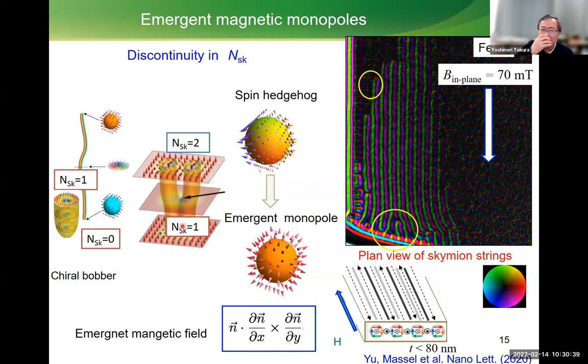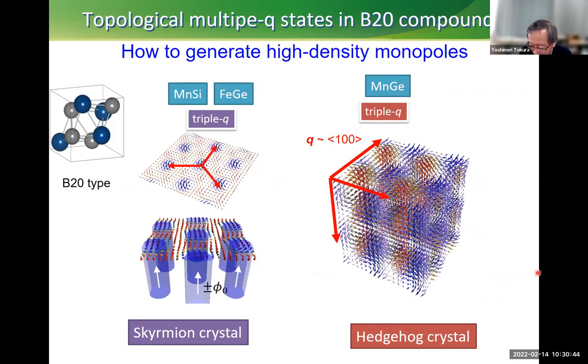However, my point is, of course, such a localized, sparsely populated monopole is also interesting, but in order to deduce a very interesting emergent electromagnetic response from the monopoles, we need rather high density monopole crystals. How to do that? Recently, we could find a very good way. One is picking up not only manganese silicide or iron germanide, the most prototypical B20 compounds, which show a triple-Q structure, the two-dimensional skyrmion, and in three dimensions the skyrmion string structure is realized. But we just replace silicon with germanium, and then we have a triple-Q structure in three dimensions. The Q vectors are along the 1,0,0, 0,1,0, 0,0,1 directions, so that we can observe the hybridization of the 3Q structures in three dimensions.